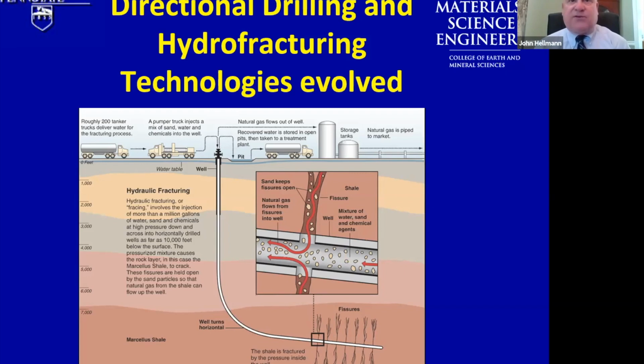These deposits are on the order of 6,000 to 8,000 feet deep. And so this is a very long drill string that once turned can extend on the order of a couple miles. Those drill bores are then cased with steel, cemented with grout to the surrounding rock so that you have a relatively impermeable barrier and hermeticity to the surface so that you can avoid contaminating groundwater. You then subsequently introduce shaped charges into the wellbore, and these shaped charges are used to blast holes through the wellbore, creating fractures in the surrounding shale.